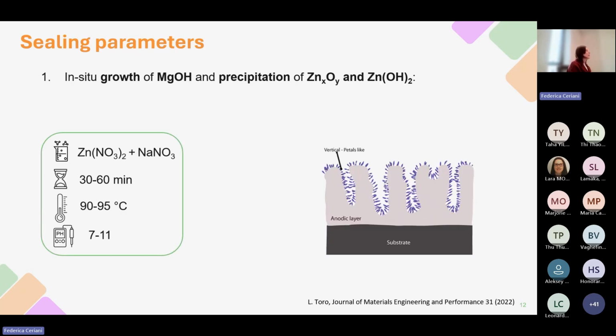Concerning the sealing post-treatment, the PEO-coated samples are immersed in a solution containing zinc and sodium nitrate heated to 90-95 Celsius degrees. Different treatment times as well as different pH of the sealing bath are tested. During this phase, the in situ growth of magnesium hydroxide as well as the precipitation of zinc hydroxide and oxide take place, providing the physical barrier effect mentioned before.